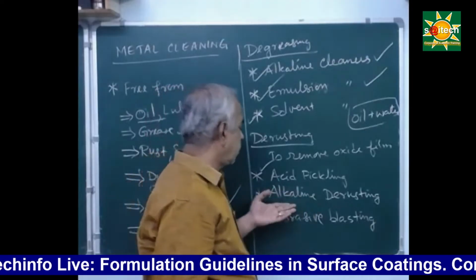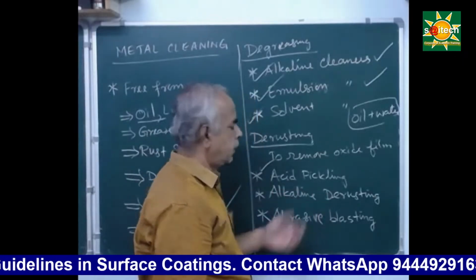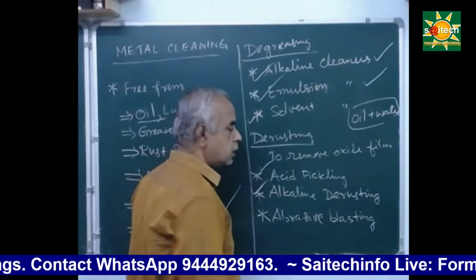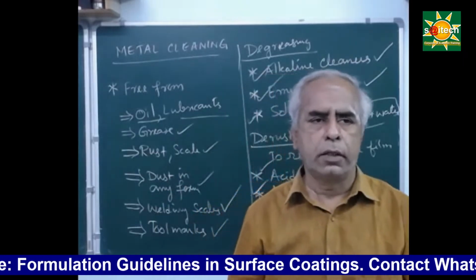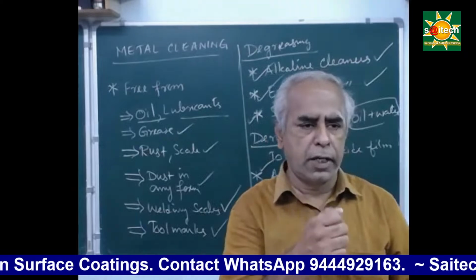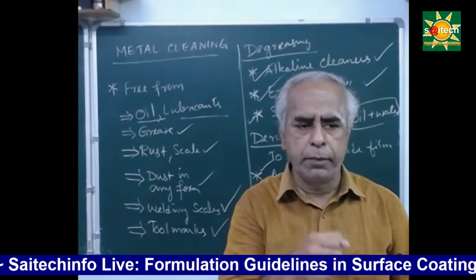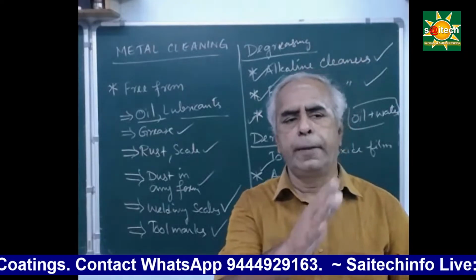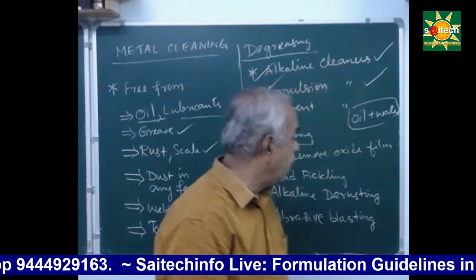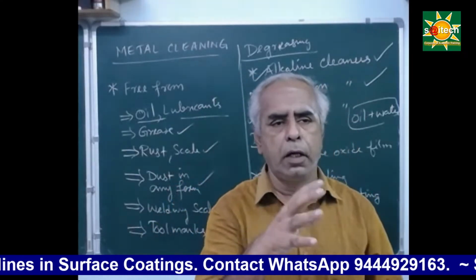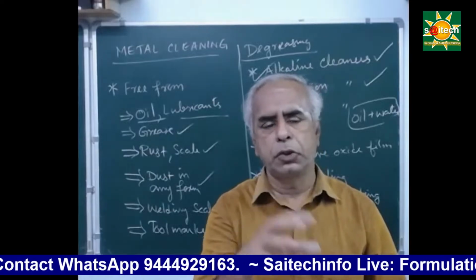We can make use of alkaline chemicals also for de-rusting. And in certain cases, physically we can do abrasive blasting, that is, sand blasting or grit blasting. Pressurized sand is made to impact the components, so that with high pressure this sand will be blasted on the rusted or scaled metal components, so that the cleaning can be effectively done. But essentially, after sandblasting, you must be sure that these trapped sand particles and other dust are thoroughly cleaned before painting or plating or zinc phosphating.